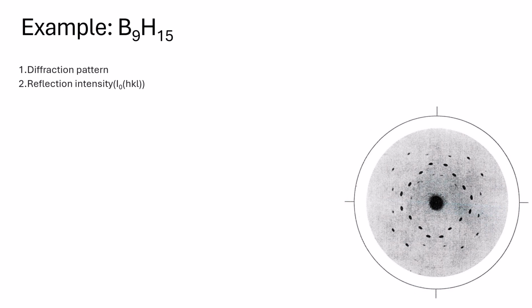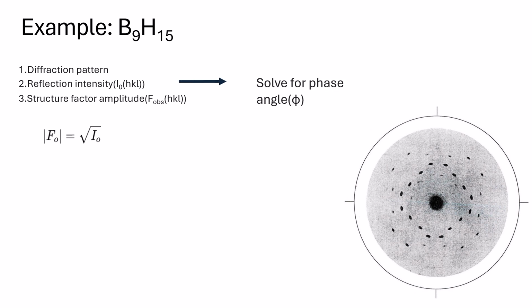It also provides data about the diffraction intensities, and with intensity we can calculate the amplitude by simply taking the square root. We get the absolute value of the structure factor amplitude. With all these data, we can start to solve for the phase angle, which prepares us for the Fourier synthesis. By plugging in the variables right here, we can find the electron density maps.